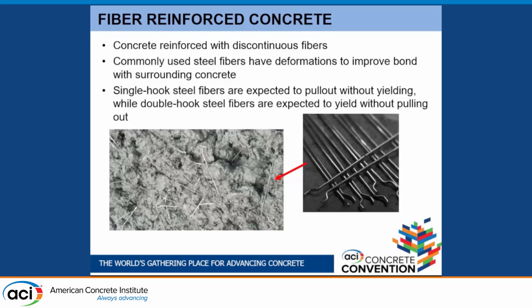Now, there are more modern fibers that have more than one hook, so they have multiple bends at the ends, and these fibers then are designed to not pull out, but rather to yield along the length, and they have to be made with a very high strength steel, and also they have to be a little bit longer to prevent fracture at relatively small crack width.